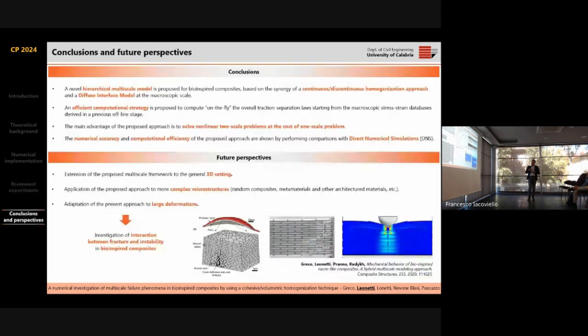So we are rather satisfied by our results, which encourage us to continue this way and propose more efficient multiscale models. So, in conclusion, a novel hierarchical multiscale model is proposed for periodic microstructures, in particular for quasi-brittle composites, based on the synergy between the continuous-discontinuous homogenization approach and the diffuse interface model. An efficient computational strategy is proposed to compute on the fly the overall traction-separation law, starting from the macroscopic stress-strain databases. The main advantage of the proposed model is to solve completely a nonlinear two-scale problem at the cost of a single-scale problem.